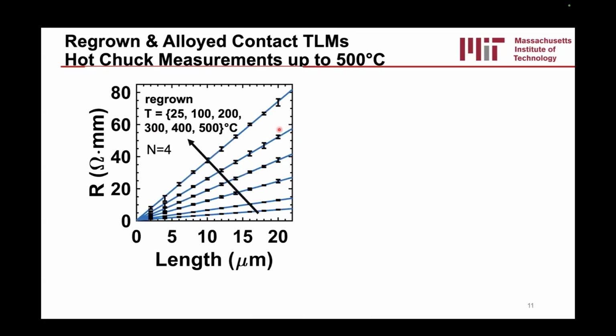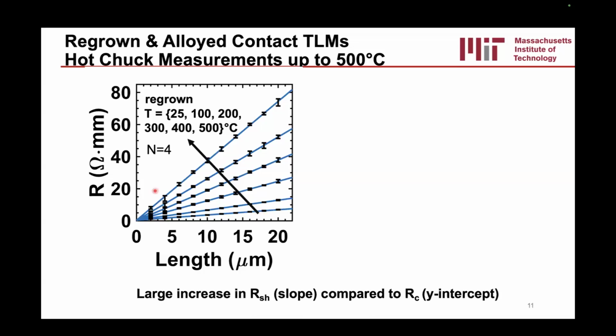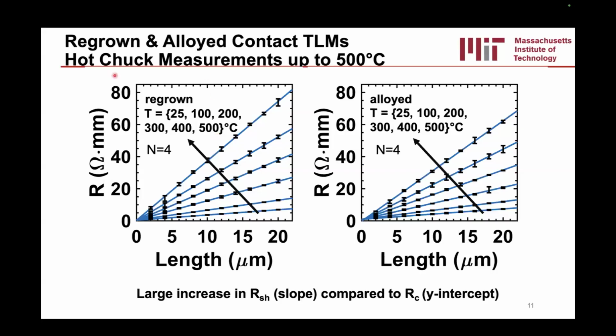Okay, so that's what we did. We did some TLM measurements where we measured those resistors for various different lengths. From the slope, we can get the sheet resistance. From the y-intercept, we can get the contact resistance. We can see that as we increase the temperature from 25 C here to 500 C, the slope increases dramatically, while the y-intercept, namely the contact resistance, doesn't change too much. We did this for n equals 4 sets of samples to have a statistically significant amount of data, and the error bars here represent 95% confidence intervals. We can do this for the sample with regrown contacts as well as alloy contacts, and they more or less look pretty much the same.